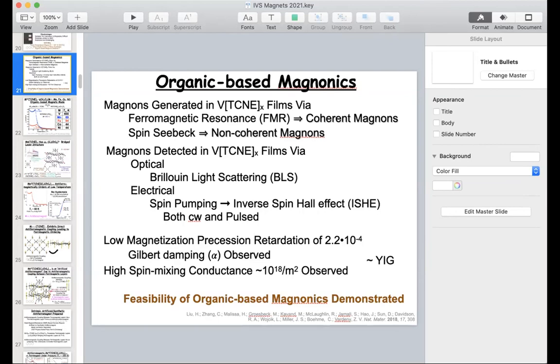And the second question: you did not speak about the crystallinity of these materials. Are they completely amorphous, or are they semi-crystalline? The vanadium TCNE materials are totally amorphous. All the other magnetic materials that we have made, some that I talked about, some I didn't, are crystalline and diffract. Some are big enough for single crystals, some are not. We can only study them by powder diffraction, but they do diffract. The vanadium one does not have crystalline order.